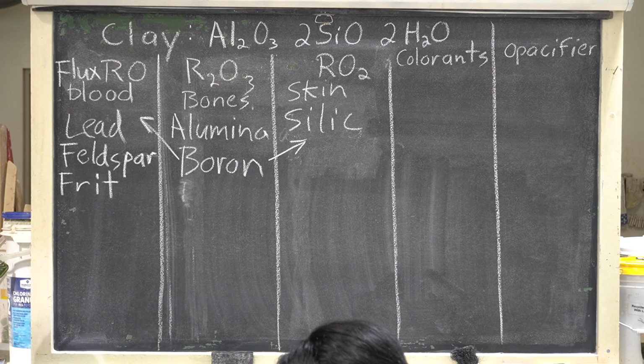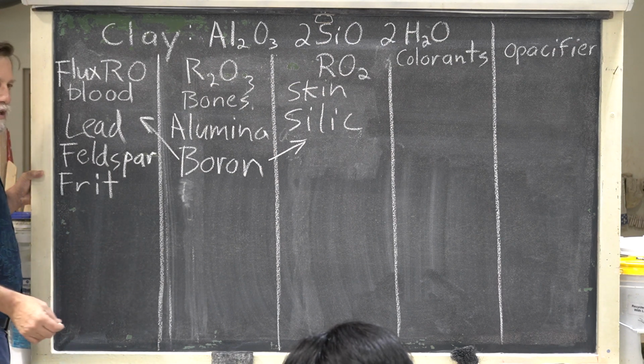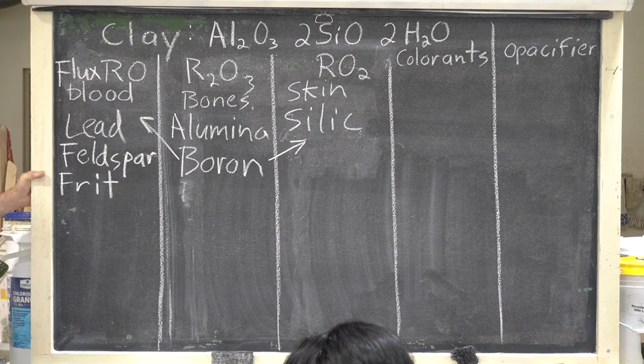There are also some naturally occurring frits. One we use a lot, though the mines may not last, is Gerstley borate. They've closed the mines a couple of times, until they realized a lot of potters would buy the materials even if they weren't pure enough for industry. It's a borosilicate flux, like an impure form of colemanite.